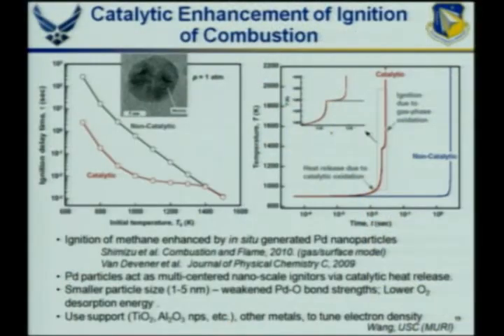Adding a catalyst, we reduce the ignition delay time by a couple of orders of magnitude. And here, these nanoparticles, we didn't even add nanoparticles. They added a palladium-containing solution. Those nanoparticles formed in situ. Hai Wang of USC did a lot of modeling, extensive modeling, and basically what he found is that these nanoparticles that are formed act as multi-centered nanoscale igniters.